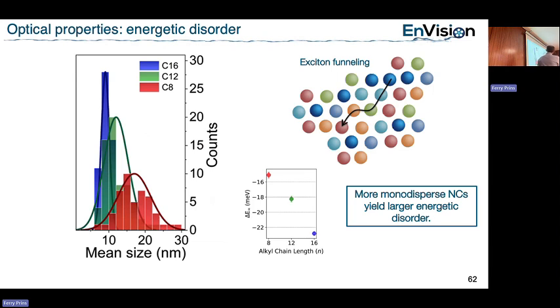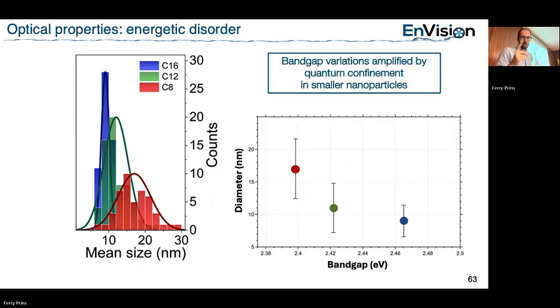If you take these kinds of particles, which are small, what we can do is plot their diameter as a function of the band gap that we measure. The diameter has a certain polydispersity, shown here as the error bar in my diameter, and then I measure the band gap energy of the different ones we measure.